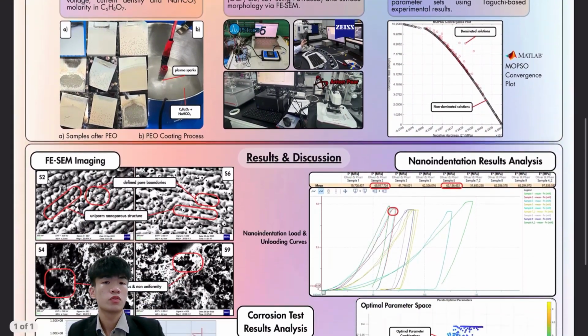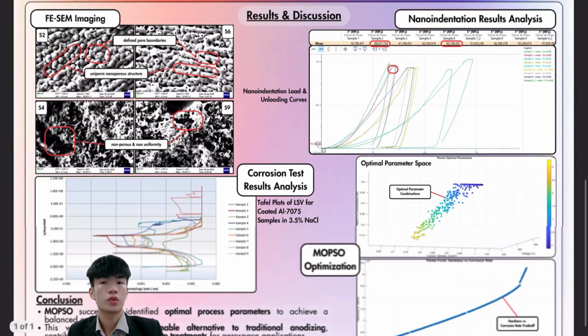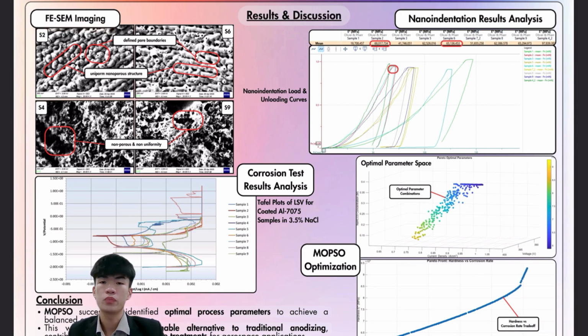Firstly, we start with the surface characterization of FE-SEM imaging. For the FE-SEM imaging analysis, only the best and worst coatings are shown here due to limited space. So samples 2 and 6, as shown here, were categorized as best as they exhibited uniform nanoporous structures with well-defined pore boundaries, which indicated effective plasma discharge and stable oxide growth. So these correspond to better coating integrity and higher surface quality.